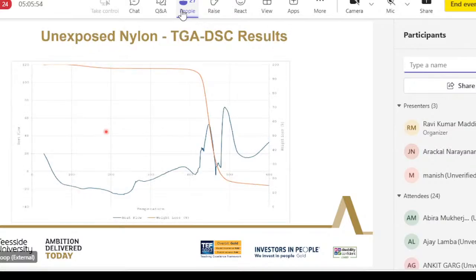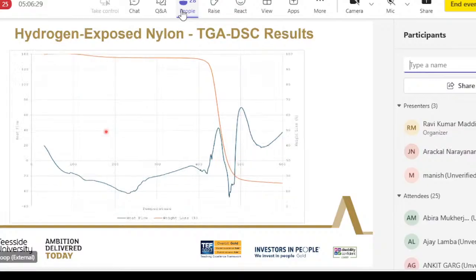If you see the DSC and TGA map, you can understand that there's not a huge difference in the material behavior, but you can see that the degradation of the material has changed. The char that is developed at the end of the process has changed. The decomposition has happened at a slightly lower temperature, which means there is some weakening of the material. A lot of studies are in progress. This is just early results, but we are still exploring this direction a lot, on understanding how different materials work in the hydrogen environment.